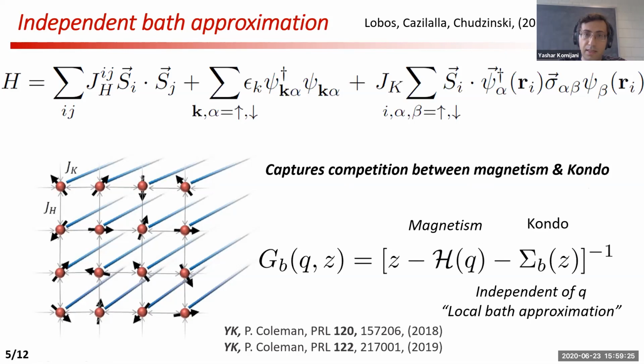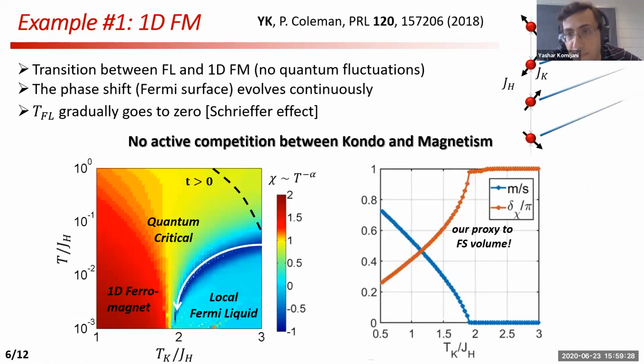All right, so let me show you 2 examples. These 2 examples will be both 1D Kondo lattices, and one case will be ferromagnetic and one case antiferromagnetic. Either way, if the Kondo coupling is dominant, each moment will be screened by its own wire, and so I will have some Kondo singlet here, and the ground state would be some product of these Kondo singlets, right? Here the Heisenberg coupling between the spins is ferromagnetic. So if that one is dominant, I will have a 1D ferromagnet, which actually orders at 0 temperature, and the ground state is again a product state.